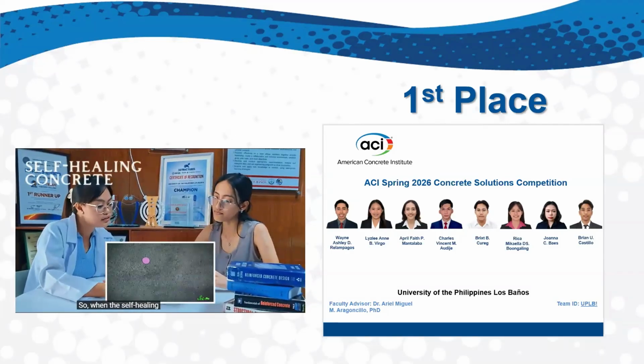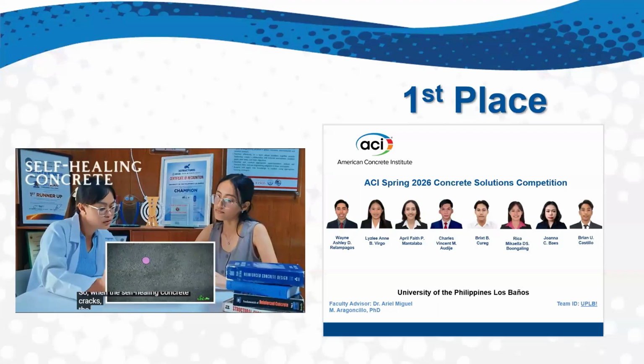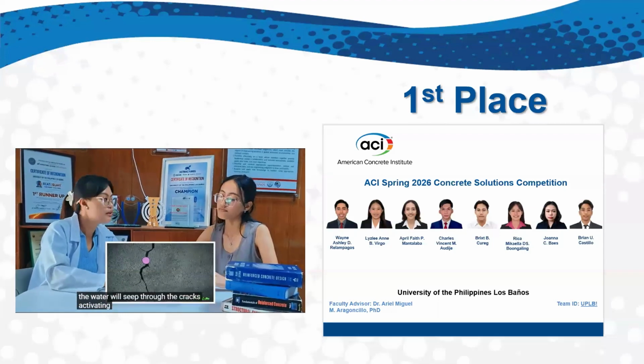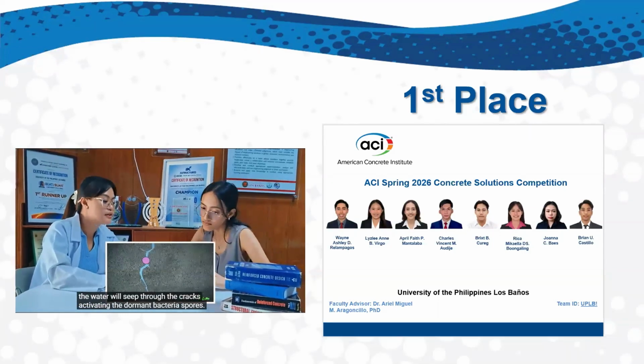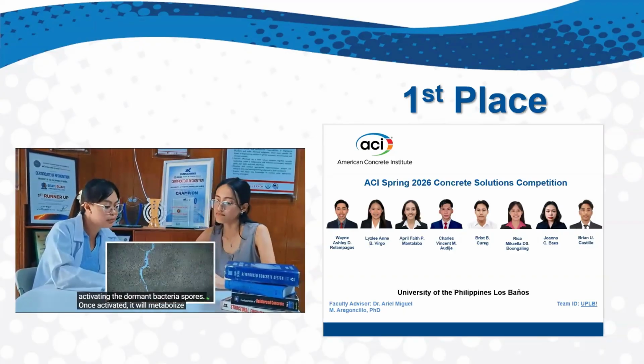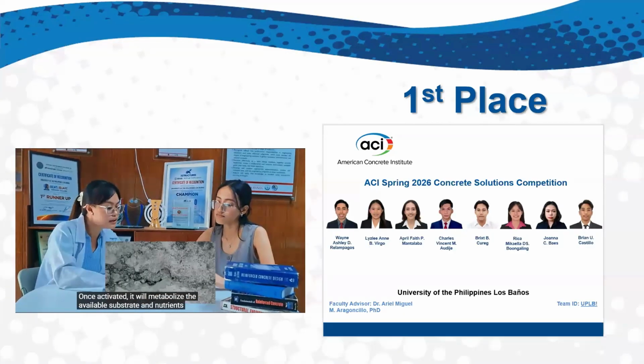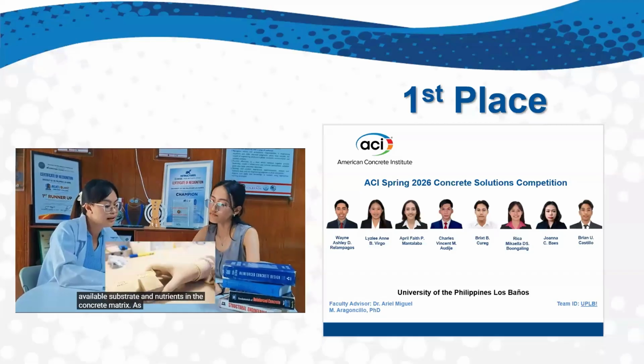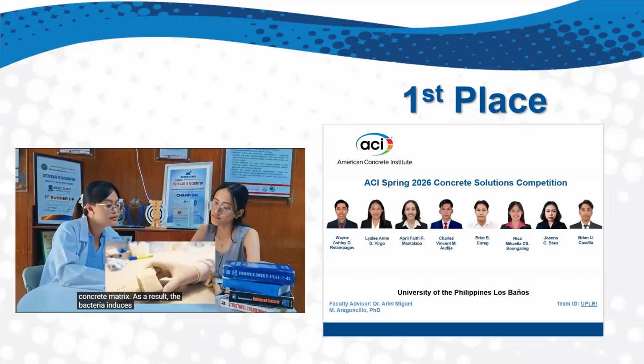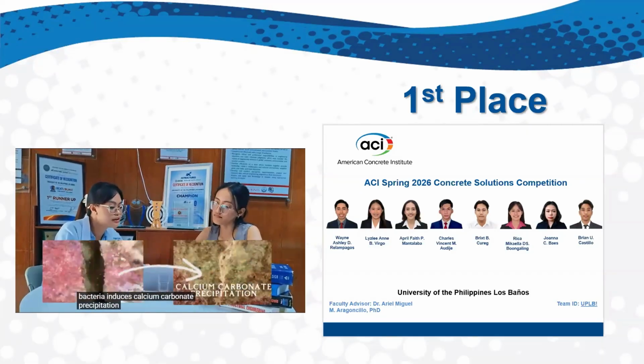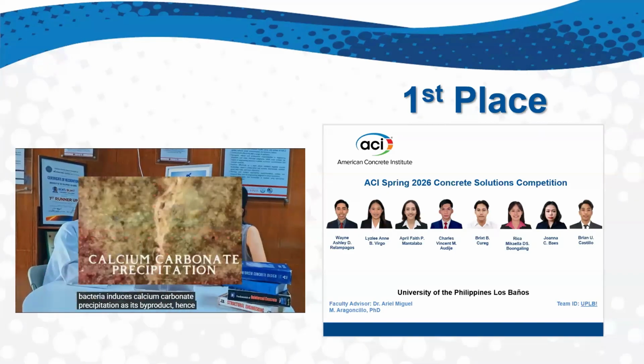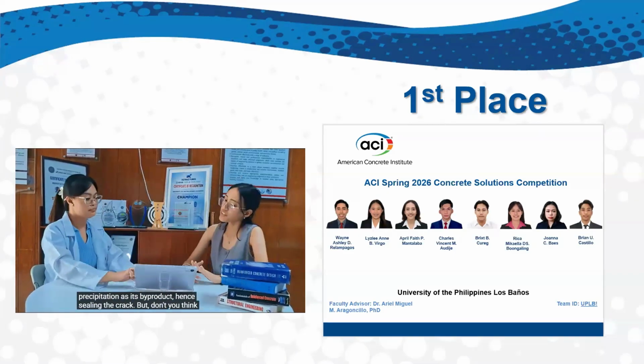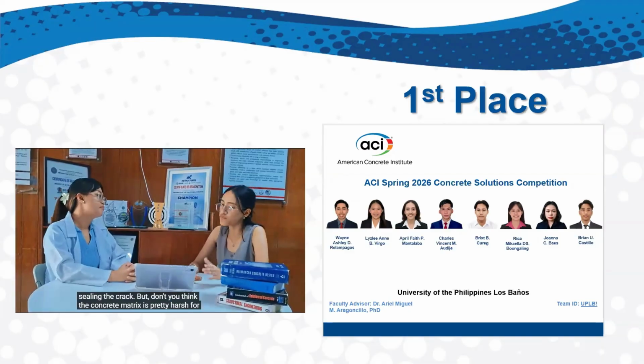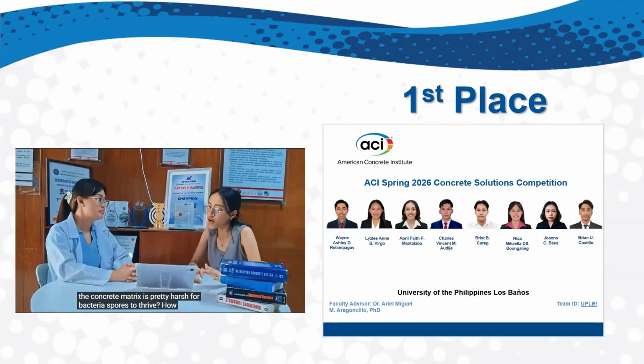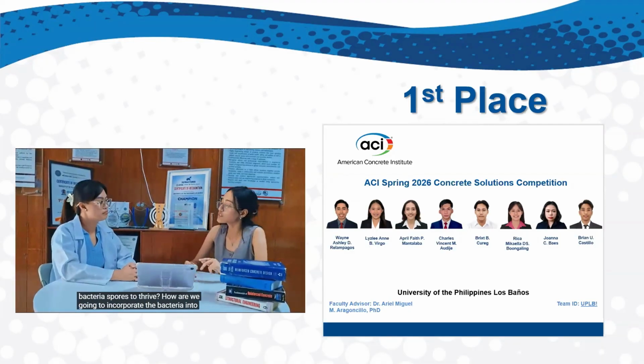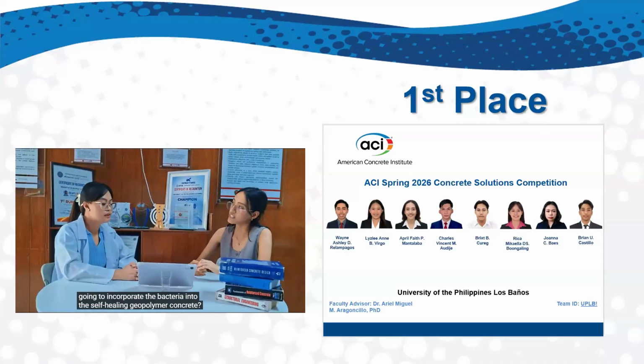So when the self-healing concrete cracks, the water will seep through the cracks, activating the dormant bacterial spores. Once activated, it will metabolize the available substrate and nutrients in the concrete matrix. As a result, the bacteria induces calcium carbonate precipitation as its byproduct, hence sealing the crack. But don't you think the concrete matrix is pretty harsh for bacterial spores to thrive? How are we going to incorporate the bacteria into the self-healing geopolymer concrete?